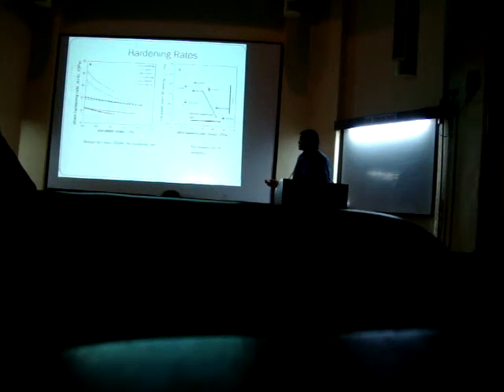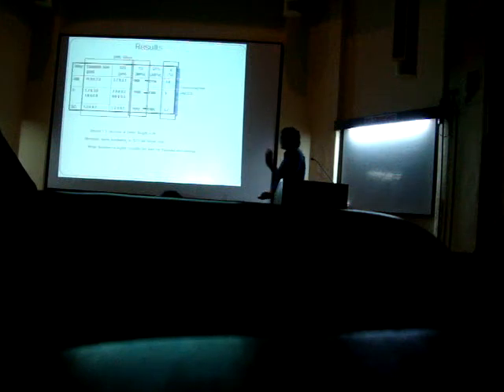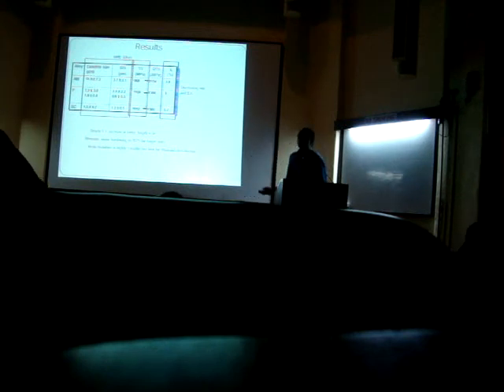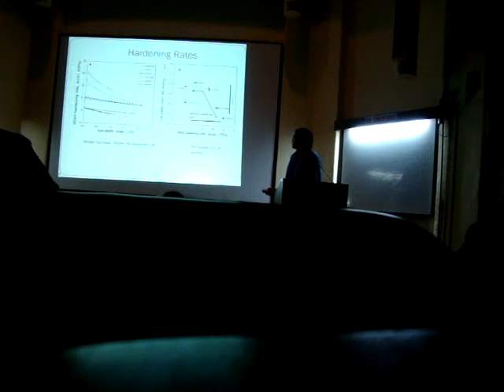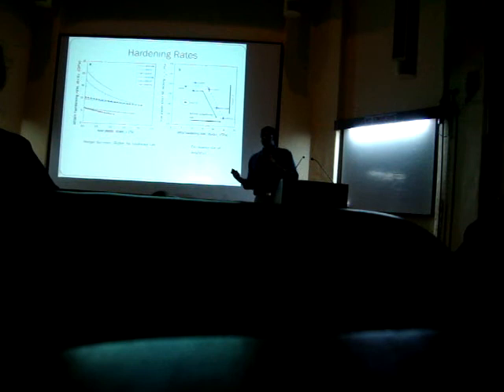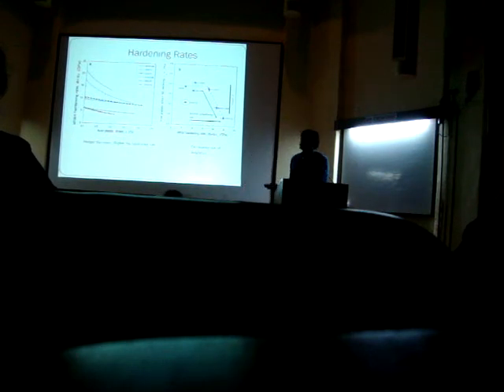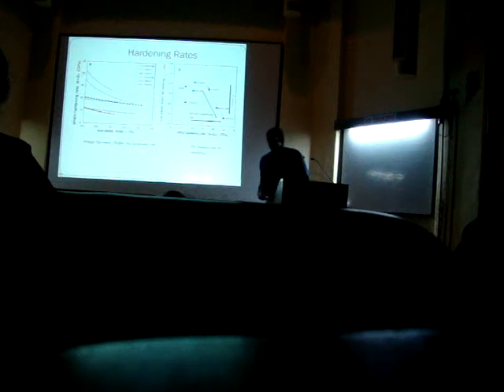So till now we see that there is a definite difference when we consider the microstructure in DH1 alloys, and that is the change in ductility. Now we look at another aspect and try to see what is changing in these alloys, and we start looking at the hardening rates, dσ/dε, and then we compare them for all the alloys, and then we plot it against the plastic strain before necking.